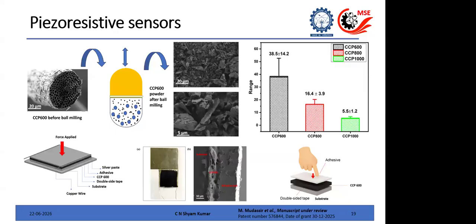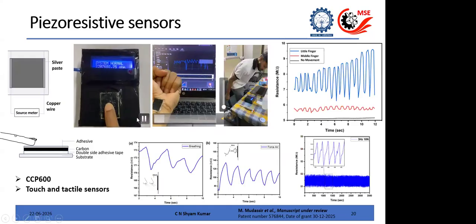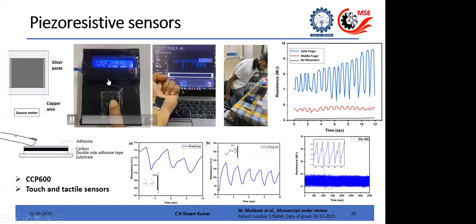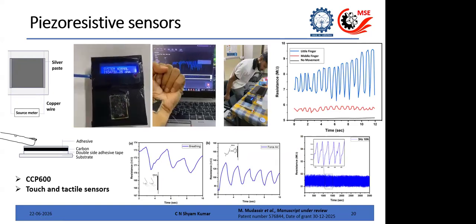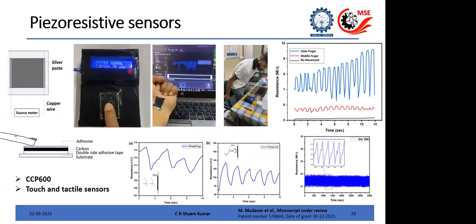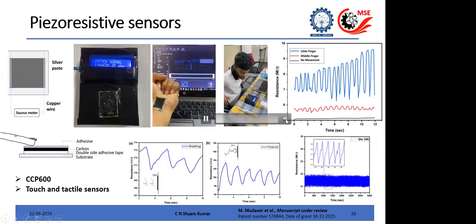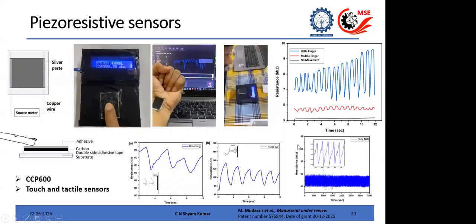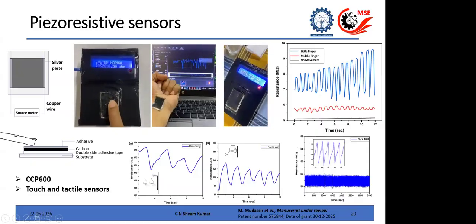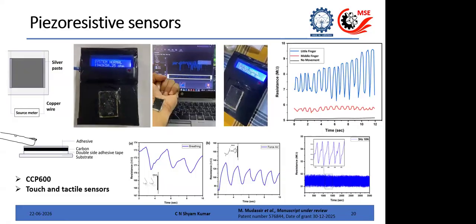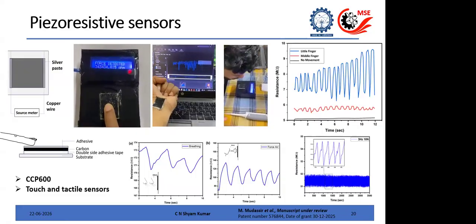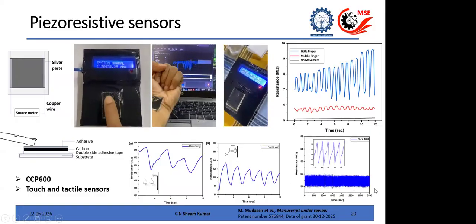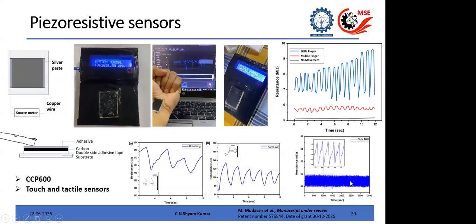If you use different powders pyrolyzed at different temperatures, you have a decrease in the piezoresistive response. This first is actually a prototype which has been working for maybe 1.5 years or so. So this means that these sensors are durable, and you can use them for motion sensing. It can also sense air flow, and you can use this as touch sensors, movement sensors, and other things. It is durable: I think more than 10,000 cycles sustained without any changes.